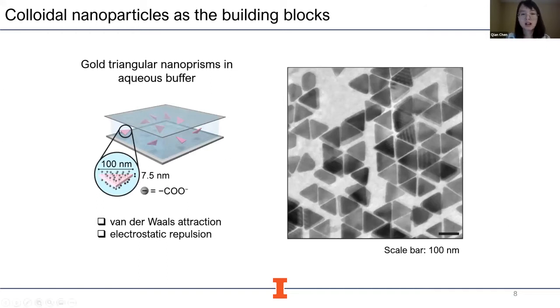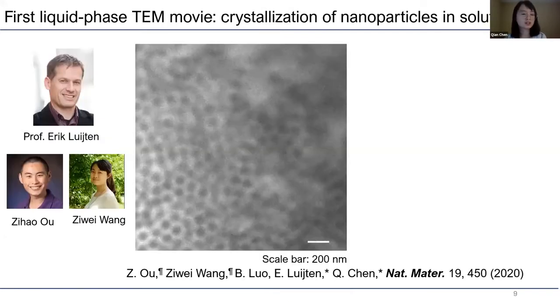You can see the size and shape in this dry TEM image. They appear dark due to the TEM contrast. The size is about 100 nanometers in length and 7.5 nanometers in thickness. On this slide, I'm going to show you a liquid phase TEM movie. Experimentally, we load the aqueous suspension of individual triangular nanoprisms into TEM, and then we trigger the crystallization in situ.